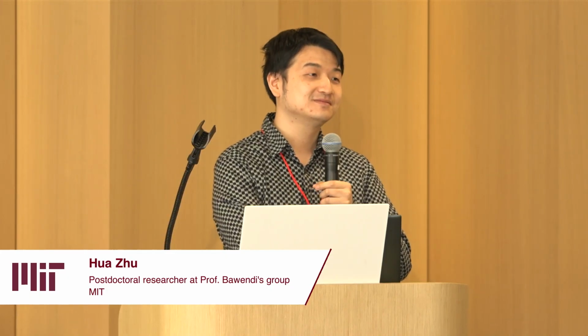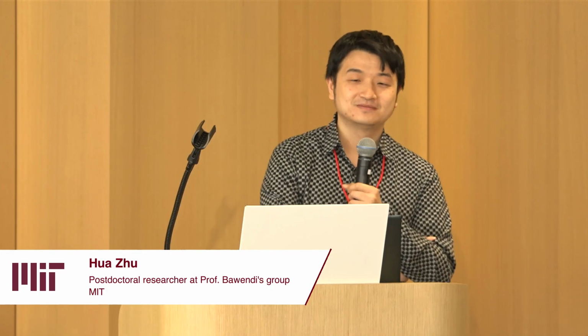Very nice talk, Hua. Very interested in your quantum dot photoresist. What's the maximum packing density that you think you can get into these imageable materials? That's a good question. We haven't reached that step, but if you think about packing, the highest packing density for dense packing is around 70-ish%, and then you have some organics in between. So this could bring the packing density down even less, but you can find ways to overcome this.